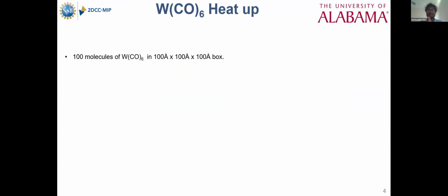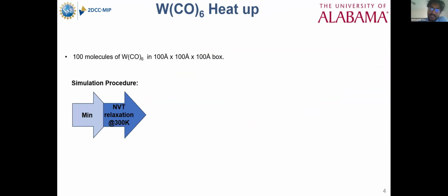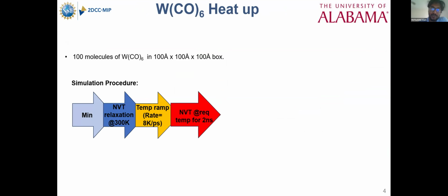With that, we went to some case studies. Like first case study, we had tungsten hexacarbonyl, and we heated up the tungsten hexacarbonyl in a box. So we had 100 molecules of tungsten hexacarbonyl in a 100 by 100 by 100 angstrom cube box. And then we first minimized the structure. We did NVT relaxation at 300 Kelvin. We temperature ramped that structure to a required temperature and did NVT at that required temperature for another 2 nanoseconds.